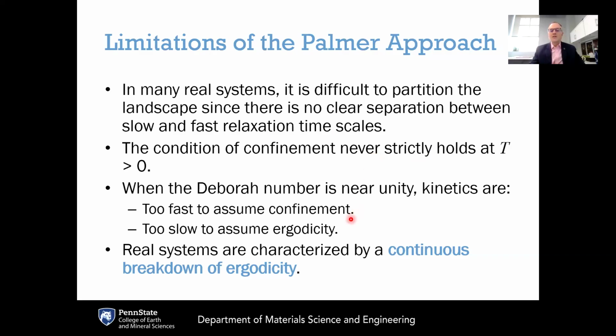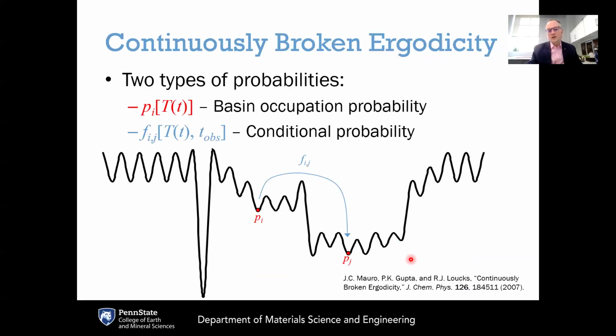Also, if you have a system that has a Deborah number near unity, so a Deborah number around one, the kinetics would be too fast to assume confinement, but too slow to assume ergodicity. And so Palmer's approach isn't particularly useful for describing systems, say, within the glass transition range itself, where that Deborah number is close to one. And so real systems aren't necessarily characterized by having this discrete transition from ergodic to broken ergodic states, but they have instead a continuous breakdown of ergodicity as the system transitions from ergodic to non-ergodic. This is a continuous breakdown of ergodicity.